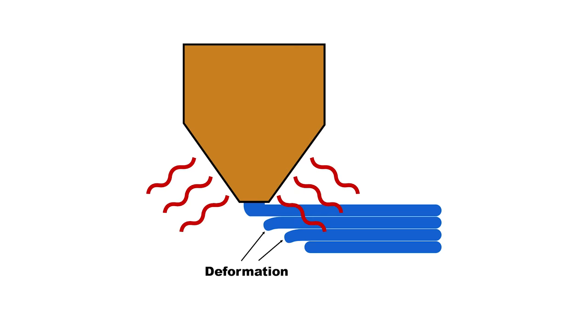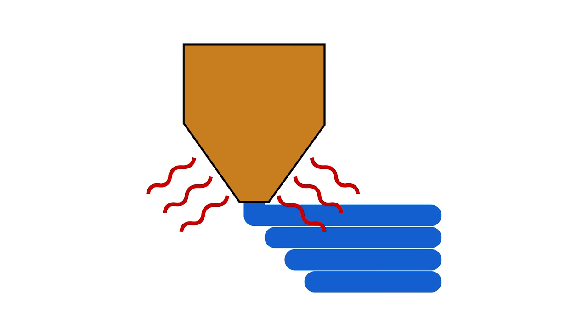So the only way around this is printing slightly thicker layers. When you do this, the thicker layers act as a thermal barrier. They prevent the radiant heat from deforming prior printed details. That's key when you're printing something like a miniature with very tiny things like noses and fingers and weapons. You want to keep those layers that you've already laid down solid, to hold their detail. If they reheat and soften, then your miniature's not going to look as crisp. For me, I like printing somewhere between 0.08 and 0.1 layer height. Once you get down to 0.05, 50 microns, it becomes so thin that you're causing prior layers to re-reach their glass transition point, and that works against you.